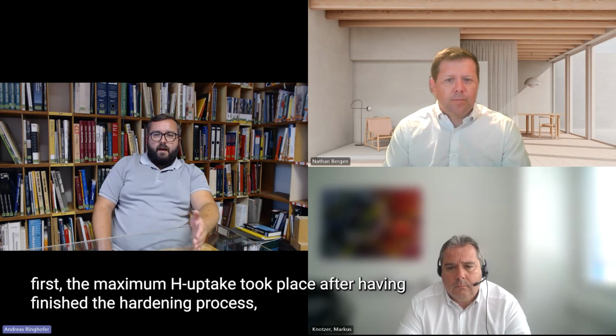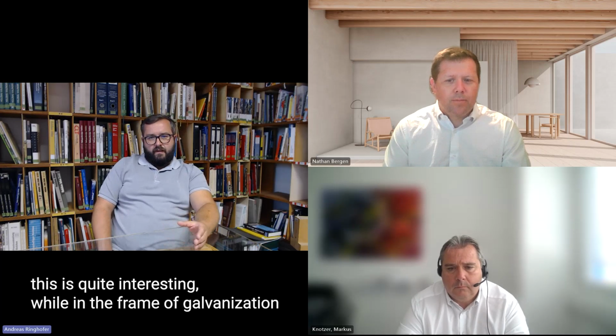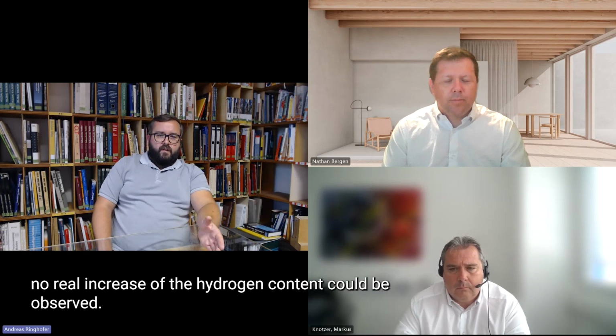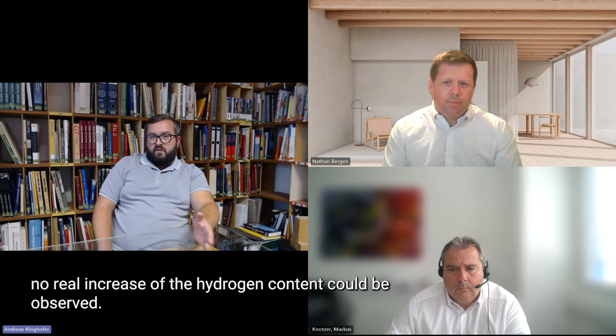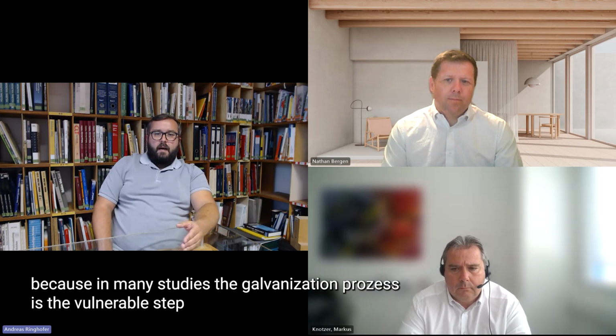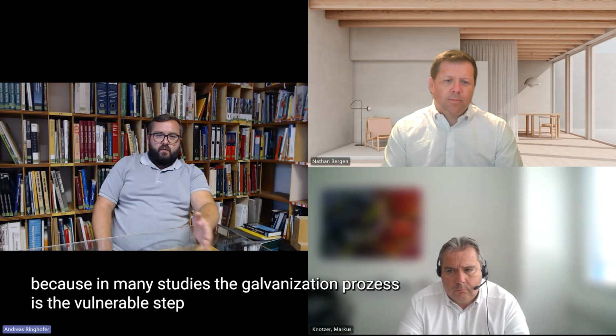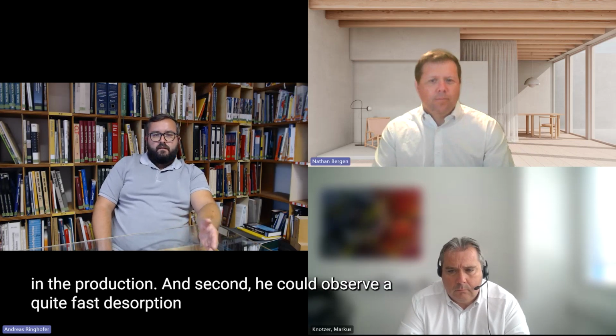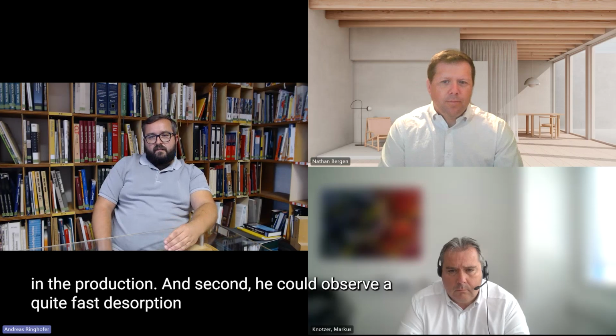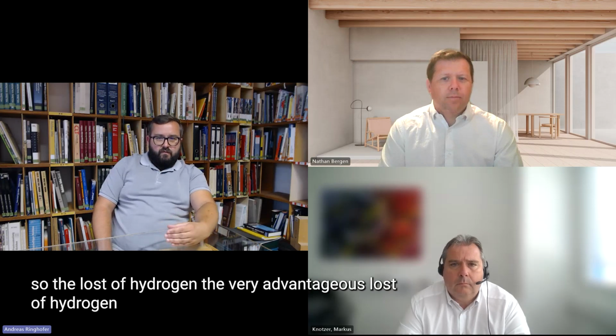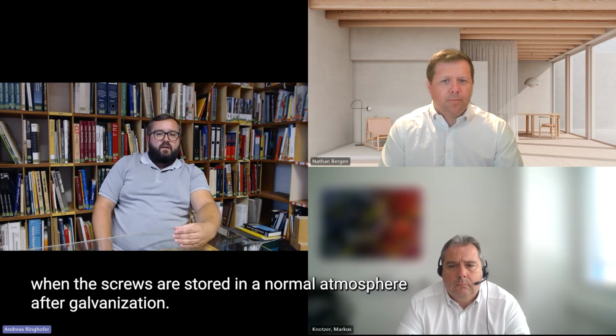First, the maximum hydrogen uptake took place after having finished the hardening process. This is quite interesting, while in the frame of galvanization, no real increase of the hydrogen content could be observed. This is interesting because in many studies, the galvanization process is the vulnerable step in the production. And second, he could observe a quite fast desorption, so the loss of hydrogen, the very advantageous loss of hydrogen, when the screws are stored in normal atmosphere after galvanization.